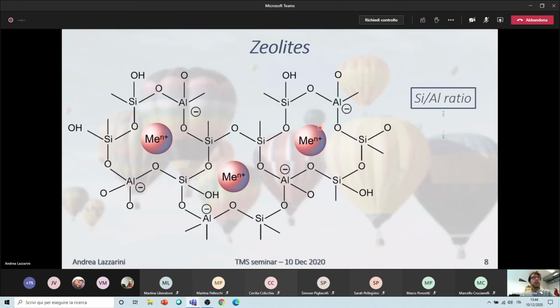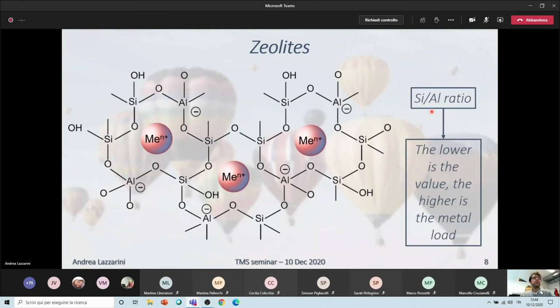And so again, we define the silicon-aluminum ratio. This time, instead of the acidity, if we have a higher presence of aluminum inside the lattice of the zeolite, we can have a higher metal loading. That means a higher activity of the zeolite.